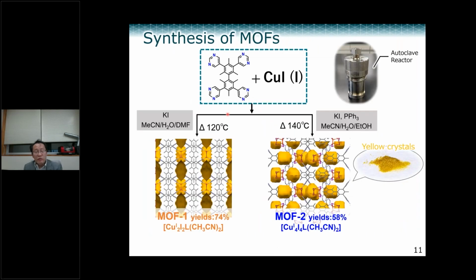According to this slide, we made two types of MOFs. This is a container, a so-called metal bomb. Using this ligand and copper iodide, where the oxidation state is 1, under this condition we first obtained MOF-1 here, in 74% yield, which is quite good. Then if you heat at 140 degrees Celsius, the major product is MOF-2.